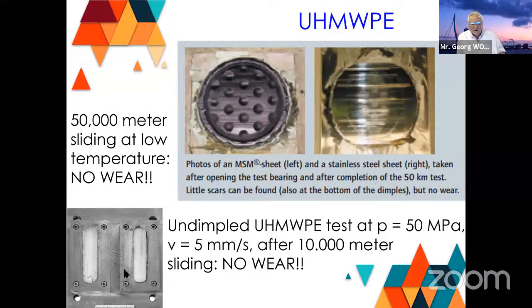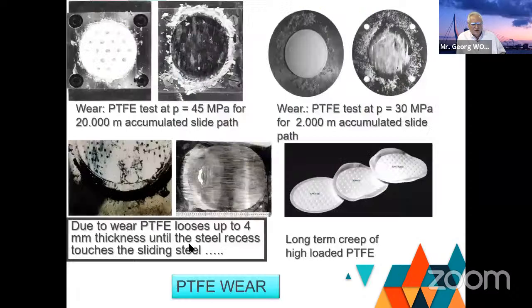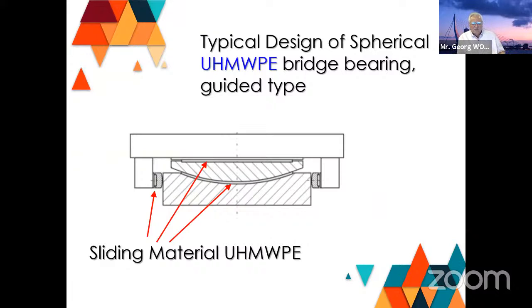Below you see the dimpled material which is used for the guides, and here also a test with a high load of 50 megapascal. After 10,000 meters, nothing is visible anywhere. If we go back again to the PTFE, then it's very obvious what a big difference there is here. So this material can be used in the spherical bearings. You can have the rotation with this material. You can have the sliding movement and also the guides with the material.